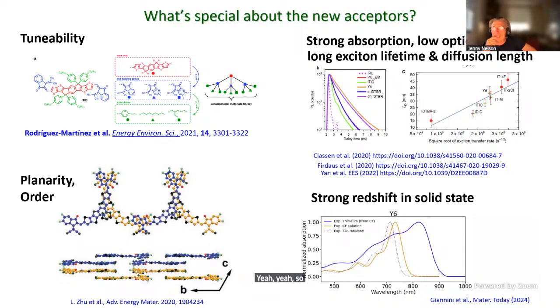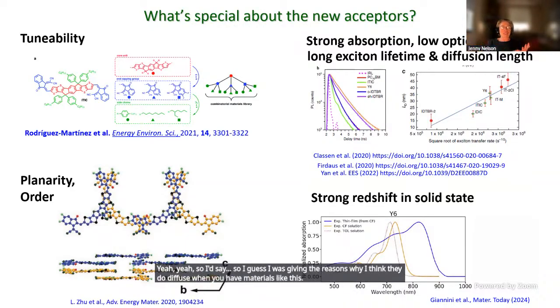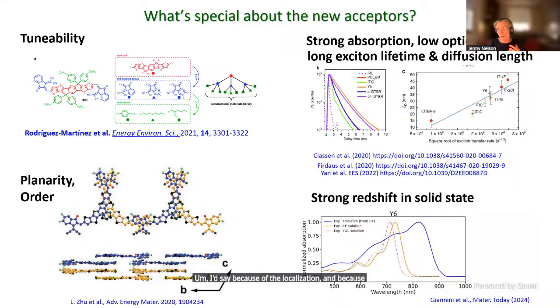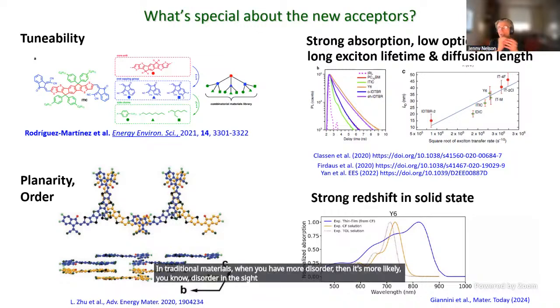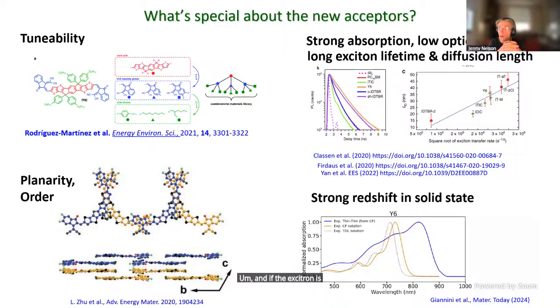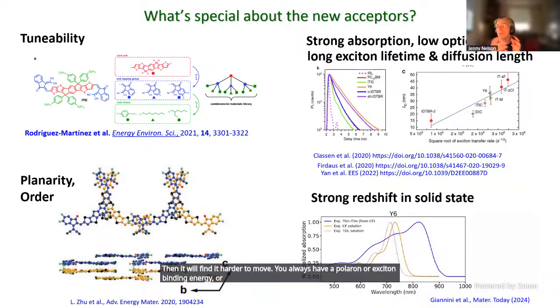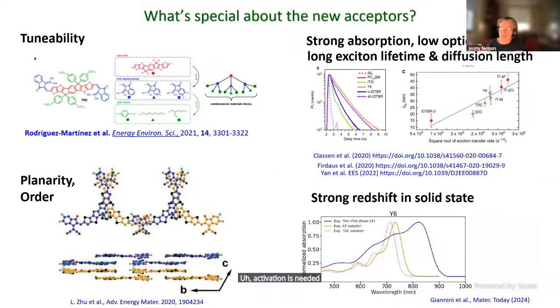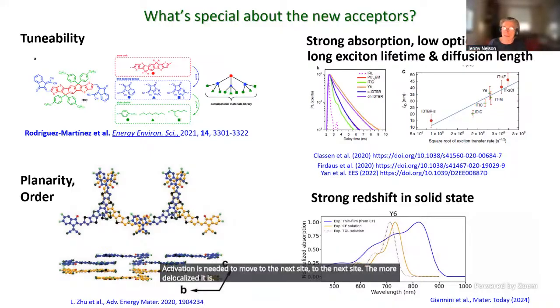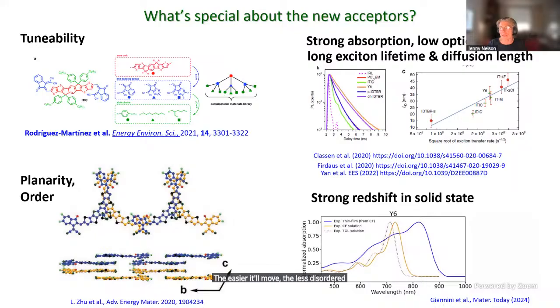So I guess I was giving the reasons why I think they do diffuse when you have materials like this. I'd say because of delocalization and because the amount of disorder is relatively low. In traditional materials, when you have more disorder in the site energies for the excitons, they're more likely to get stuck. And if the exciton is strongly localized, so not delocalized, then it will find it harder to move. You always have a polaron or exciton binding energy or whatever. Some activation is needed to move to the next site. The more delocalized it is, the easier it'll move, the less disordered it is, the less likely it is to get trapped.